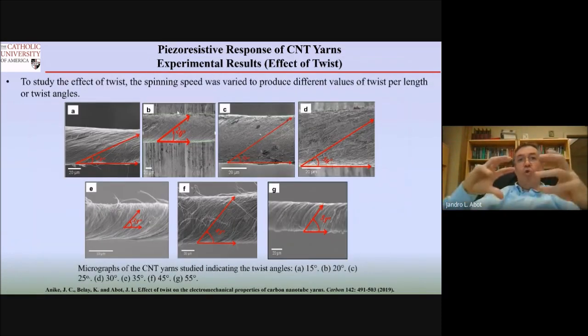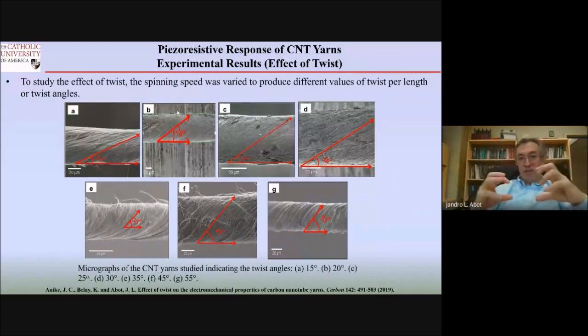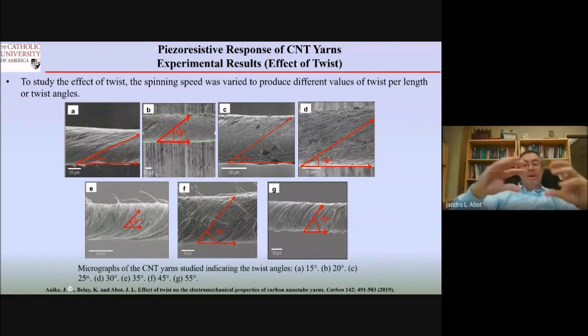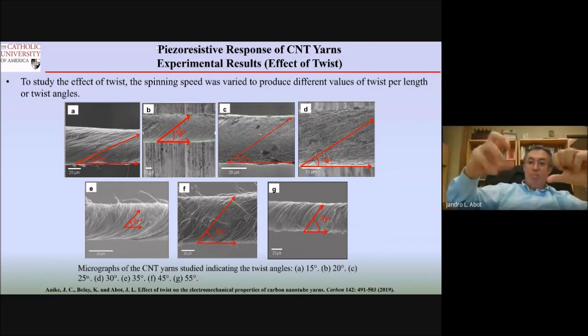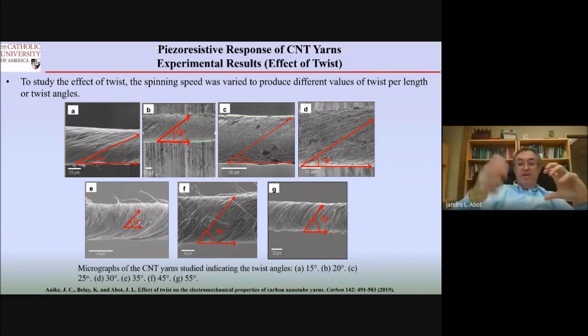For example, when you form the fiber, the angle of twist that you exert also plays a role in that response. Typically the fiber that we use has an angle of twist of 30 degrees. By the way, if you pull the nanotubes and form the fiber and you don't twist them, you basically have no stiffness. The material is like a loose assemblage of nanotubes. When you twist it, the material becomes a lot stiffer, a lot easier to handle. The more you twist, the stiffer the material will be, and the electrical response will be different as well.